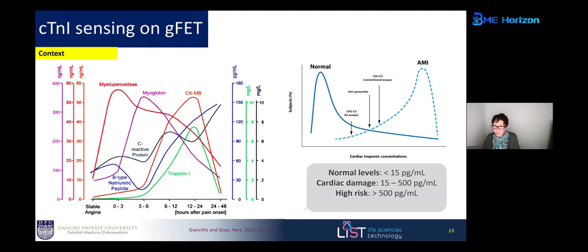So the next thing you have to take into consideration is detection limits, because this will be important when we design our sensor. Normal people have levels below 15 picograms per milliliter of this cTnI. Small cardiac damage is between 15 and 500. And if you really have high levels, you're already at very, very high risk. So what we want to do with our sensors nowadays is to be able to distinguish between the three levels: people who are not ill, people who probably have an onset of damage, and people who are already at very high risk, with cTnI in the blood.